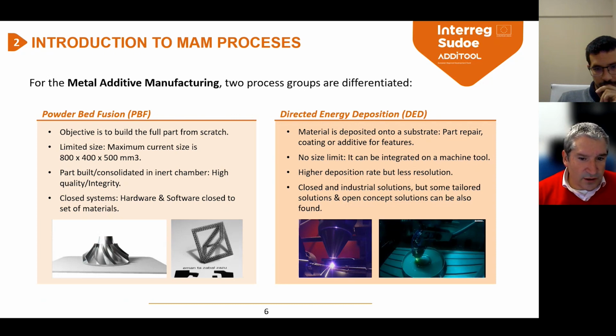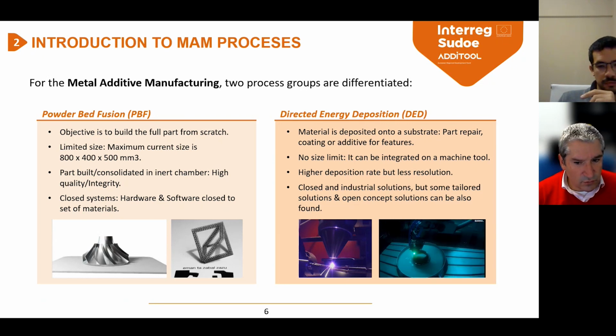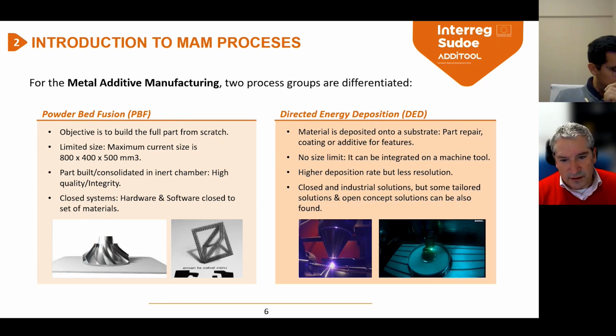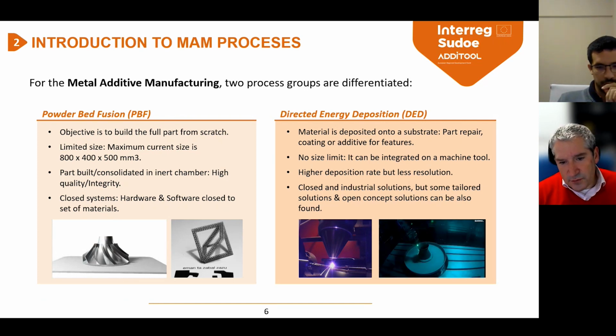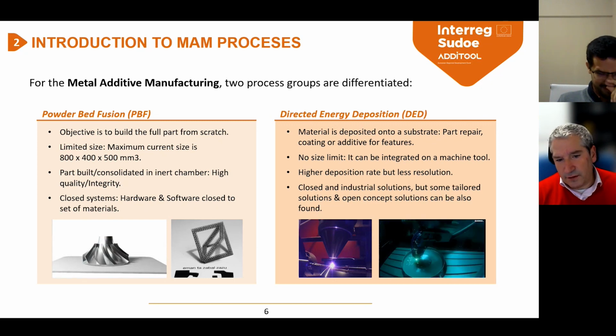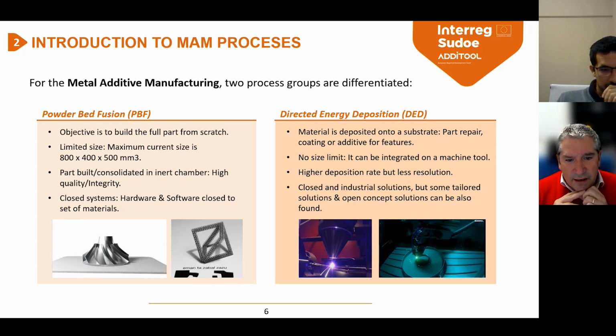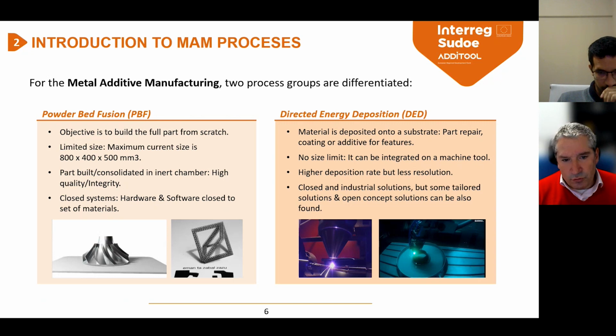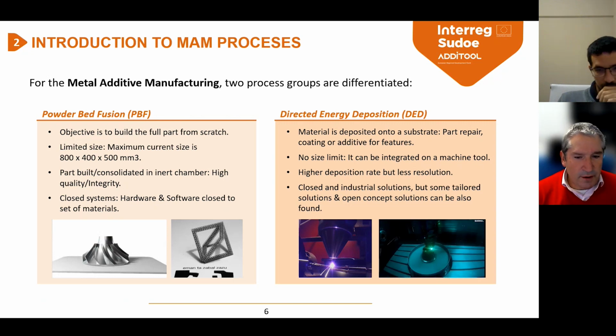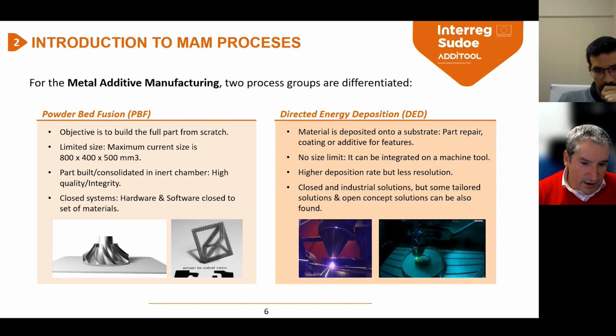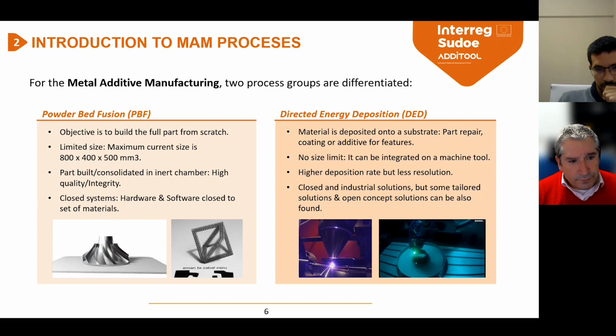In that case, we do not need an inert chamber, since the inert gas is injected directly with the nozzle, with the system that injects the material. So the inert atmosphere is provided directly with the nozzle, and it gives us the opportunity of going to a very big part, so we can integrate this system in a very big machine tool or a robot. So the part can be larger. Okay.